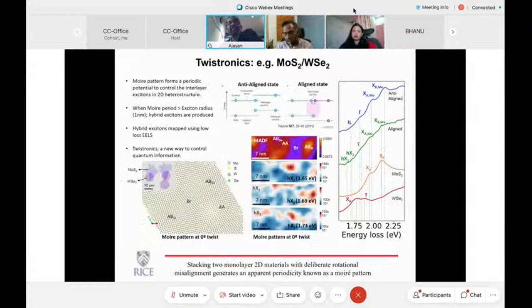Now, the other thing that I was just mentioning is this whole idea of twisted layers. So there were several studies that explored twisted bilayer graphene, and they found that if you take two layers of graphene and twist them into a certain angle, you can get some kind of electronic interaction leading to superconductivity. So these twisted bilayers were seen to be a potential superconductivity candidate. And after that, people were fascinated by this whole idea that you could take any two layers and put them into various moirés by twisting and get different properties. And the whole field is now called twistronics. And there's large funding provided for creating these moiré layered structures.